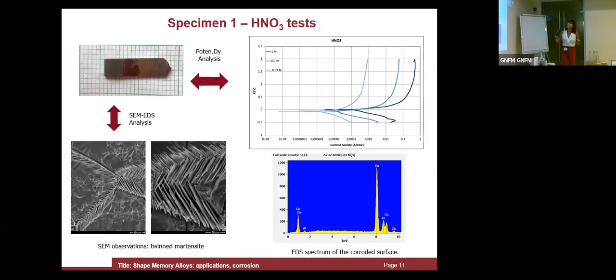Okay, here we have the sample after the first potentiodynamic test in nitric acid. I would like to show you this SEM observation. This is a chemical image where the different gray levels respect the composition. It's not a photo. And here we have the characteristic formation of twin martensite. So the movement that I described before is well represented here, because the structure of martensite is really characteristic.